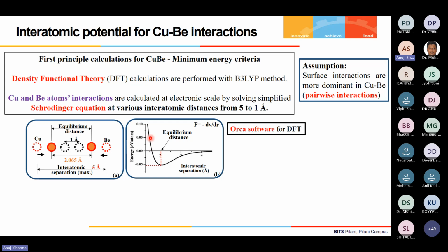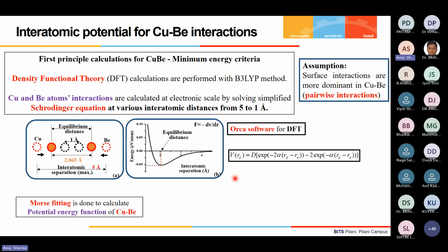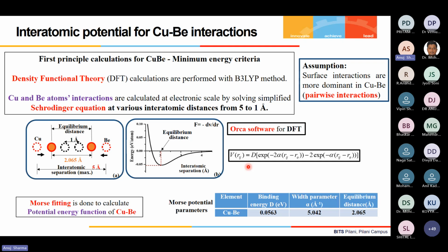So higher energy means least stability and lower energy means more stable. So here the structure is more stable. At this point, these parameters were extracted and fitted with the Morse fitting parameters. So the Morse function is this one. The parameters were evaluated: D is the binding energy, which is nothing but this parameter, minus 0.0563. Similarly, alpha is the width parameter, so how much width it assumed, and the equilibrium distance, which is at 2.065. So these parameters were evaluated, and this function was incorporated in the molecular dynamics simulation.